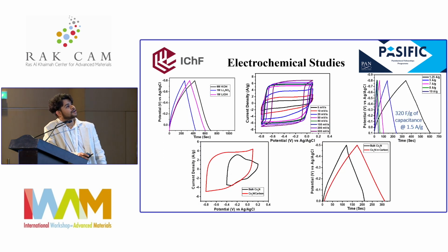After that, we did the electrochemical studies of the material. Firstly, we optimized the electrolyte. For 6 molar KOH, we got lower Coulombic efficiency, and for lithium sulfate, we got lower capacitance. So we optimized lithium hydroxide for this material. We did the CV and the GCD, and from GCD we got 320 farad per gram of capacitance when we discharged it at the rate of 1.5 ampere per gram. We also compared the bulk cobalt nitride with the material we prepared, and we got higher capacitance compared with the bulk cobalt nitride.